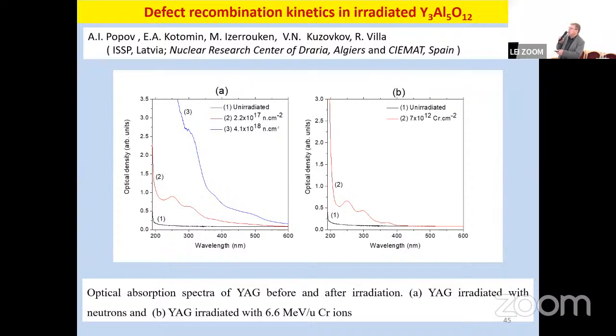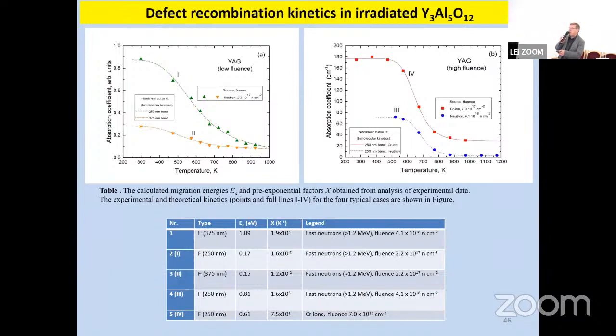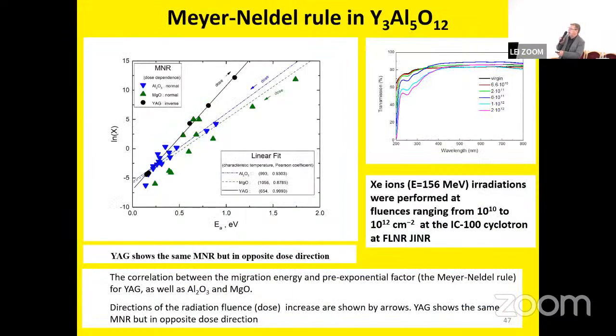As one example, we also performed measurements on such a material as YAG, yttrium aluminum garnet. We see the same behavior for neutron and ion radiation, the same type of annealing, and even the temperature range is quite similar to what we observed for spinel and for alumina. And again, my model works quite well, and you can see here for comparison magnesium oxide, alumina, and YAG. The only difference, if some of you have already seen this, is that we have different behavior of the Meyer-Neldel rule as a function of dose.